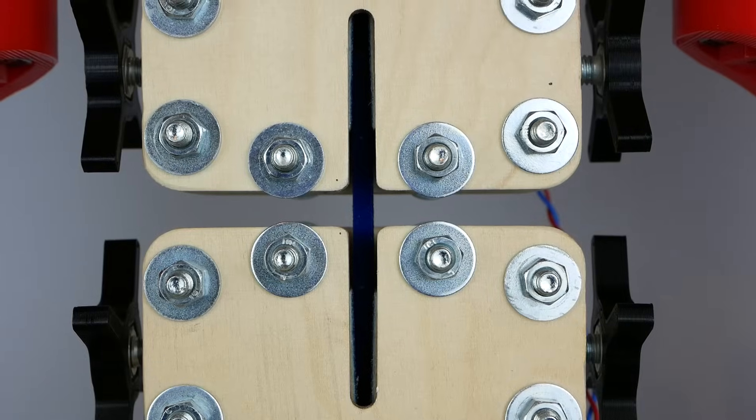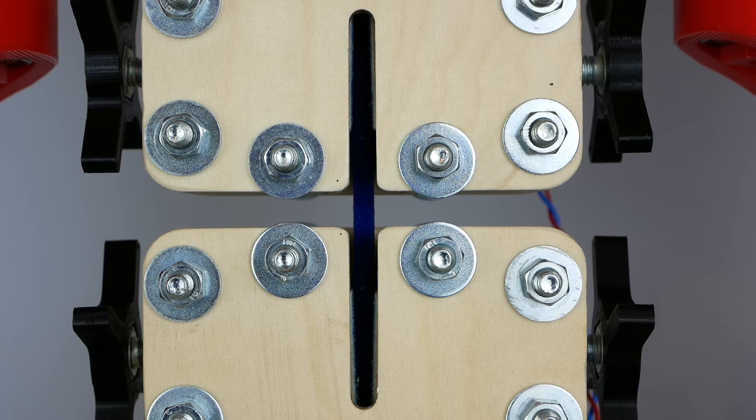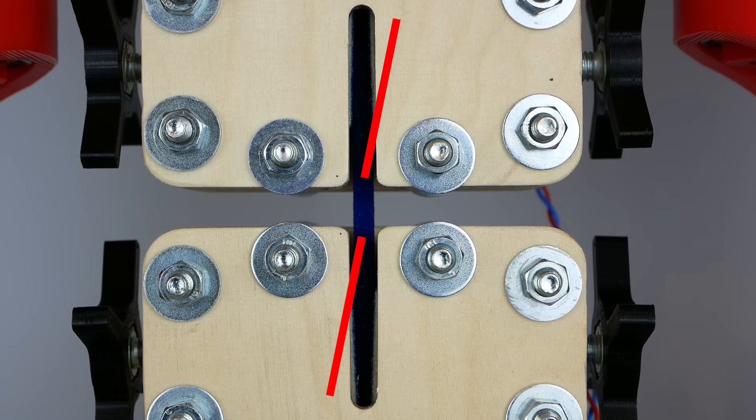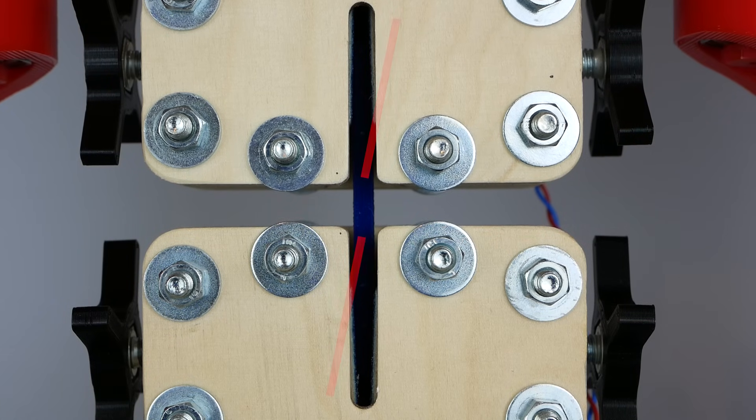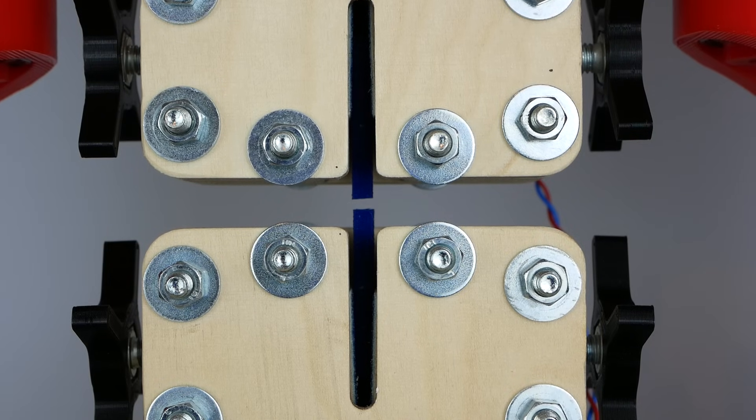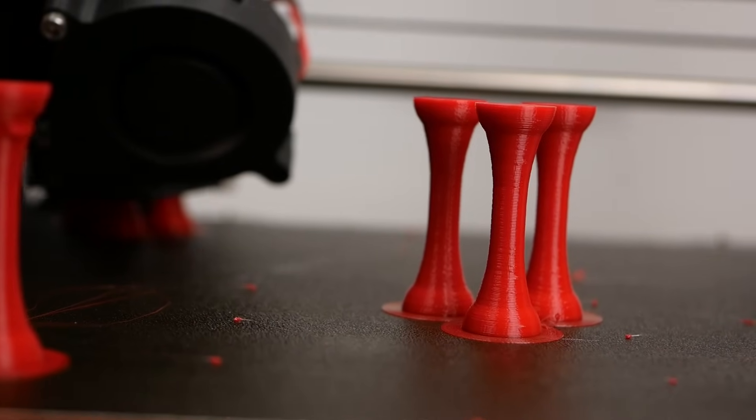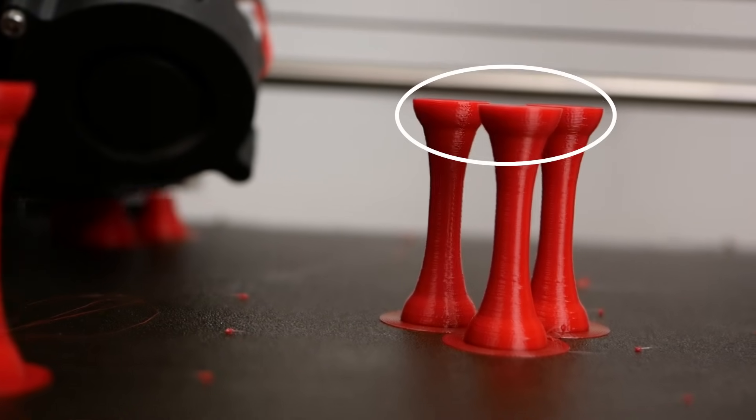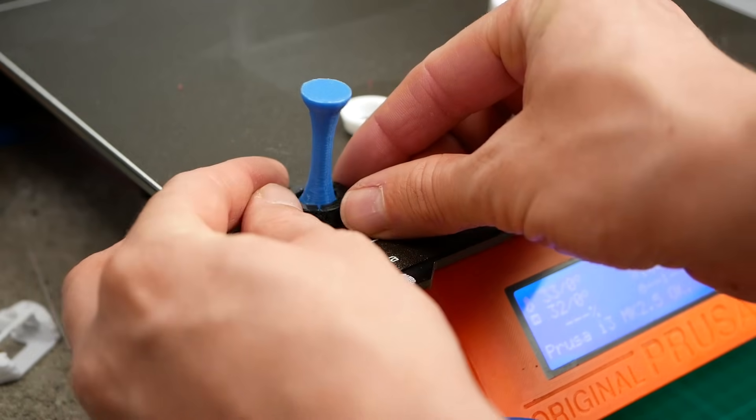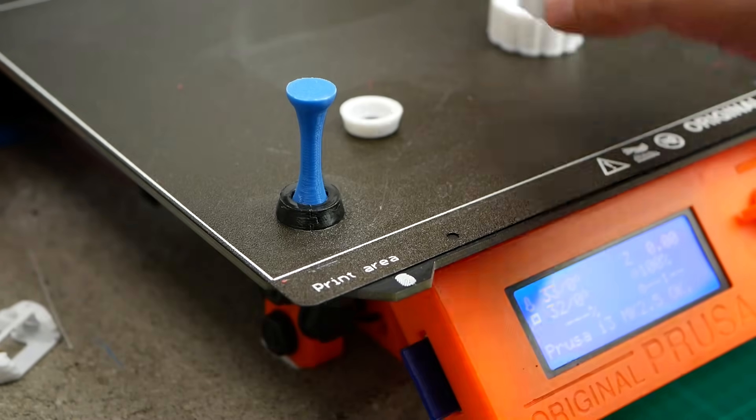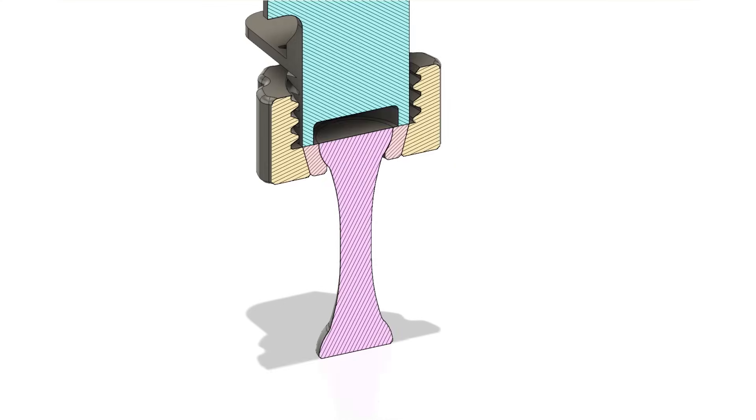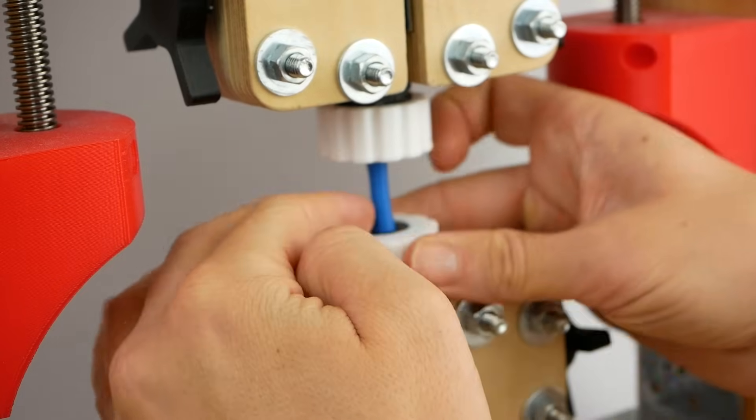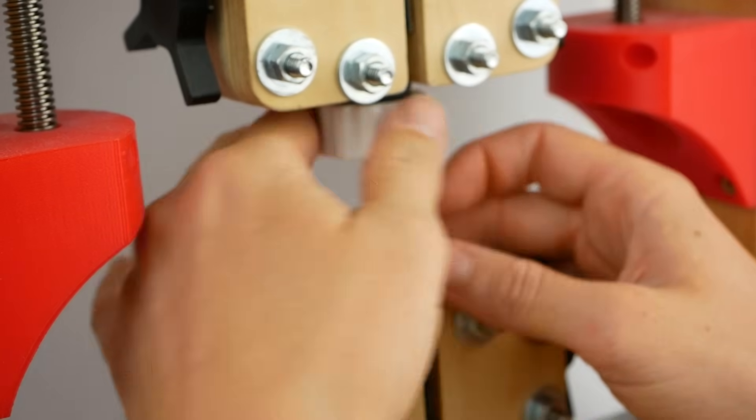Unfortunately, these specimens gave me quite some trouble in the past because if the two jaws of my test machine don't align perfectly, the coupons will see a slight bending load instead of pure tension and therefore fail prematurely and invalidate the results. For this reason, I designed a new set of samples that feature half-spheres on both ends which are still nicely printable. With a suitable sleeve and a holder, they form a spherical bearing and minimize the bending loads of the sample. This greatly reduced the scatter in my results and will be the new shape I'll use for layer adhesion tests.